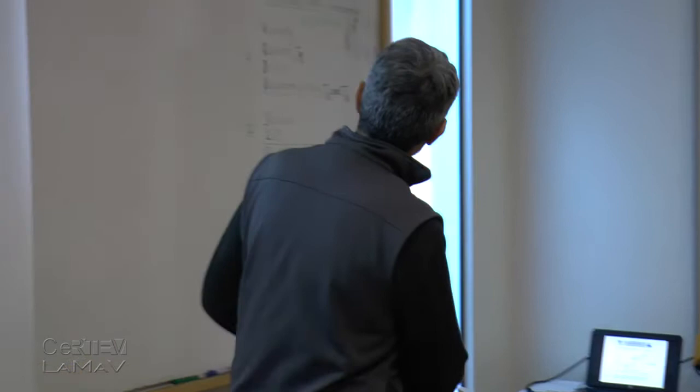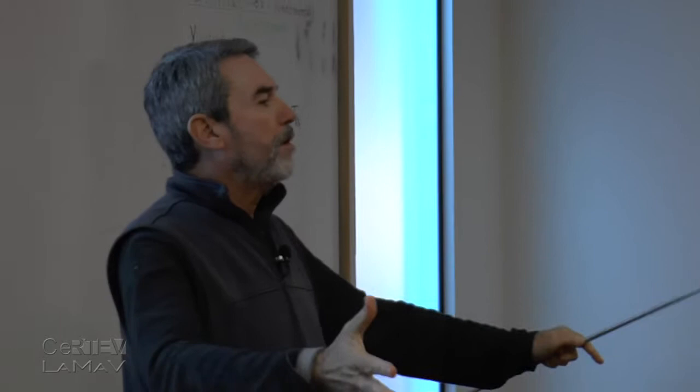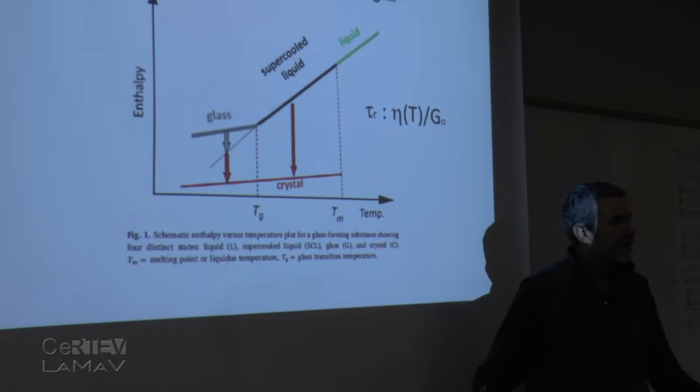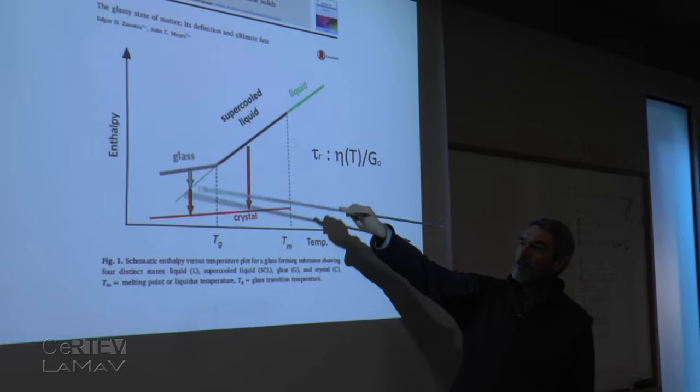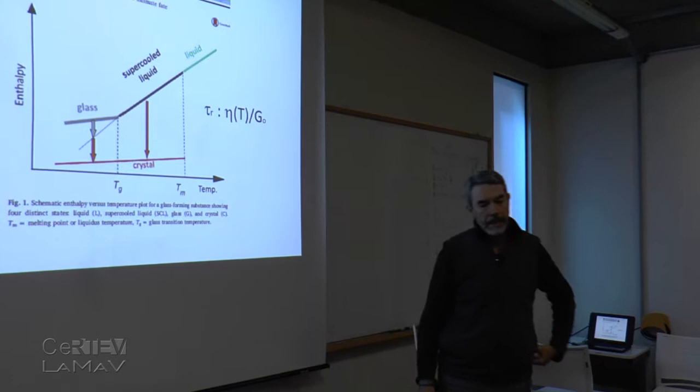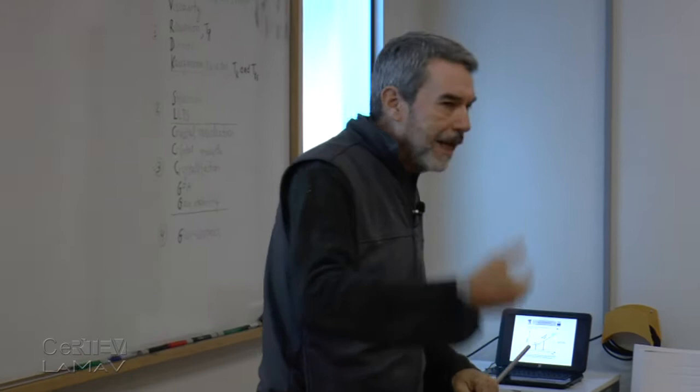And we can calculate how long it will take for a glass to relax. But glasses spontaneously relax. This is the first key feature of glasses. They will spontaneously relax. All glasses are relaxing. Even at room temperature, they are relaxing. A little bit. It will take a long time to fully relax, but they are unstable. Glasses are unstable. They will spontaneously relax. There is no thermodynamic barrier for relaxation, only a kinetic barrier. It only needs time.